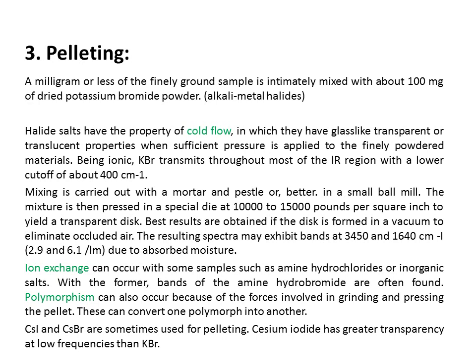Now when you do this pressing, there has to be removal of air, because if carbon dioxide is present, it is going to show its own absorption bands. Or if moisture is present, H2O is going to have its own absorption bands, fine. So you have to take care to do the measurement in a vacuum, and moisture or carbon dioxide shouldn't be there when you do the pelleting.